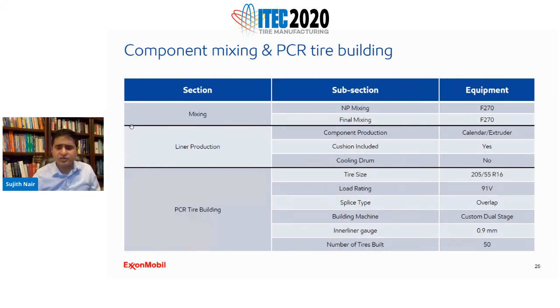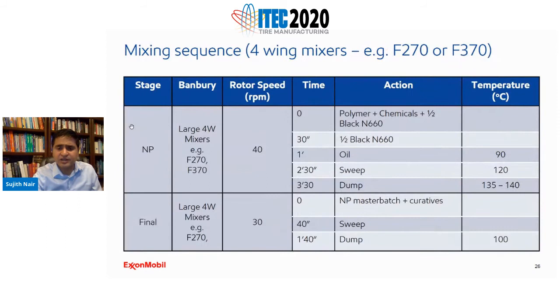And in PCR, the tire size that we are talking about is a 205/55 R16. The splice used was an overlap splice, and the building was done on a dual stage machine. The innerliner target gauge was around 0.9 millimeters, and that's where most of the innerliners landed. And basically, we have also done some statistics on all of this. The mixing procedure that we use is the standard in the industry.